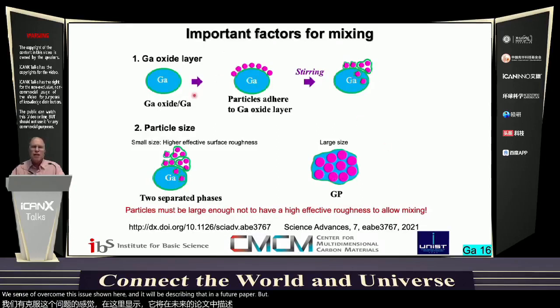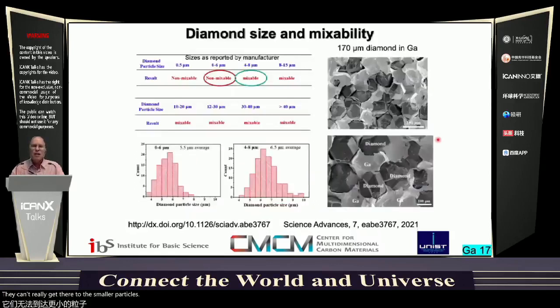But at least at the time of the work, we could not mix particles smaller than a certain threshold size. And we ascribed this to the ability, so to speak, of the gallium oxide skin to coat larger particles, but if the surface is too rough, they can't really get to the smaller particles. And so, as you can see here, the smaller particles were non-mixable and larger ones were, for diamond and all the larger ones as well. And these nice cross-section images show diamond particles dispersed inside the gallium.